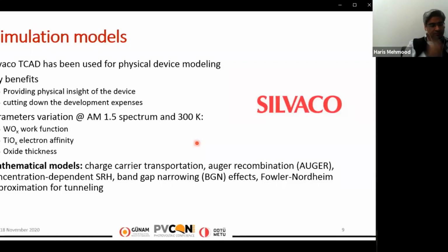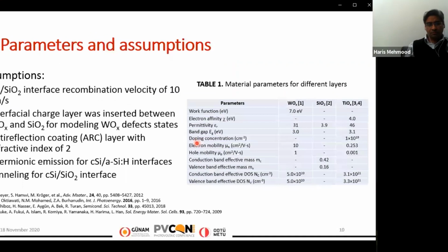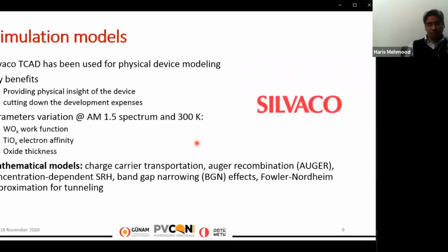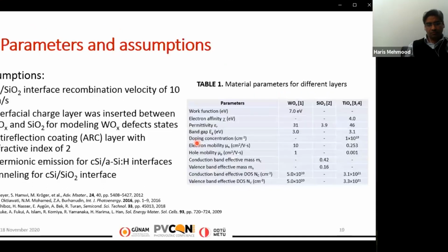Several mathematical models were employed, such as charge carrier transportation, Auger recombination, concentration-dependent SRH, band gap narrowing effects, as well as the Fowler-Nordheim approximation for tunneling across the silicon dioxide region. Similarly, several assumptions were also taken for the simulation. Shown is the table in which we have used various input simulation parameters for tungsten oxide, silicon dioxide, and titanium dioxide. The assumptions we have taken are that the interface recombination velocity was specified, and the defect density layer between the tungsten oxide and the silicon dioxide, as well as titanium dioxide and the silicon dioxide layer, was also incorporated in the simulation.